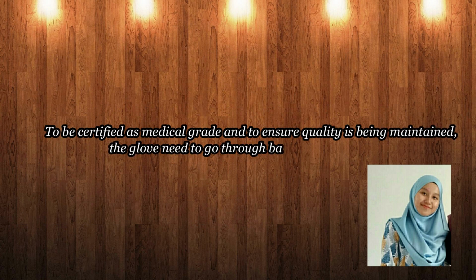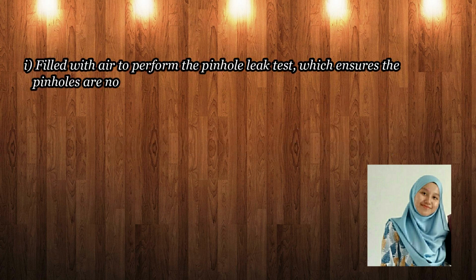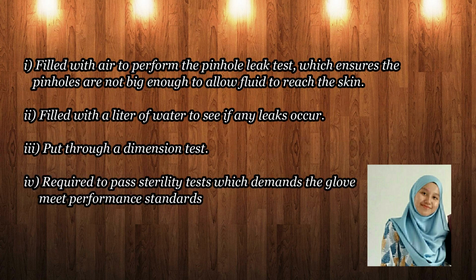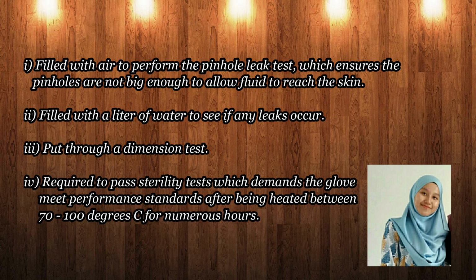Gloves must meet regulatory requirements to be certified as medical grade and then go on to batch testing to ensure quality is being maintained. For batch testing, first, the gloves are filled with air to perform the pinhole leak test, which ensures the pinholes are not big enough to allow fluid to reach the skin. Second, the gloves are filled with a liter of water to see if any leaks occur. Third, the gloves are put through a dimension test. The gloves are required to pass a sterility test, which demands the glove meet performance standards after being heated between 70 to 100 degrees for numerous hours.